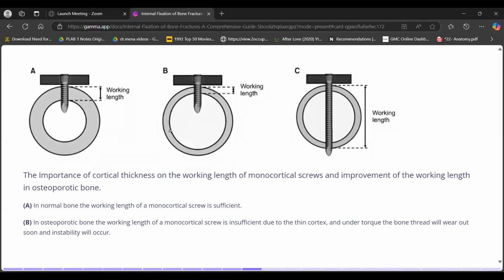Also, if you're going to use a plate, we need to check that we achieve the working length of the fracture, and it depends on the type of the bone, the mode of fixation you are using when you use a plate, and also the type of the fracture. So in normal bone, the working length of a monocortical screw is enough, but in osteoporotic bone, we need to fix the bicortex, the near and far cortex, because there is a very high risk for the bone thread to wear out, causing instability of the fixation you're trying to achieve.